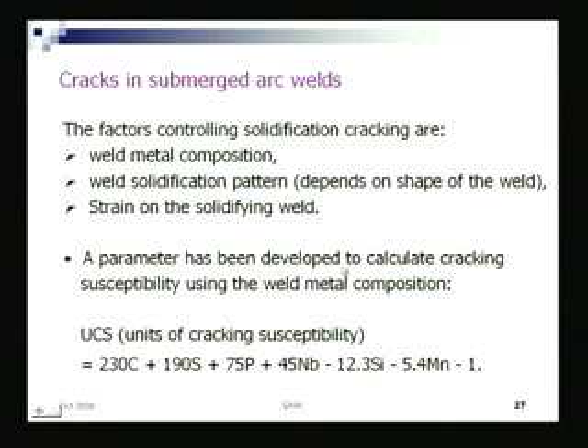So a parameter has been developed to calculate the cracking susceptibility depending on weld metal composition, because all these cracks connected with the welding process are essentially because of thermal stresses on one hand, and on the other hand, lack of ductility of the material.